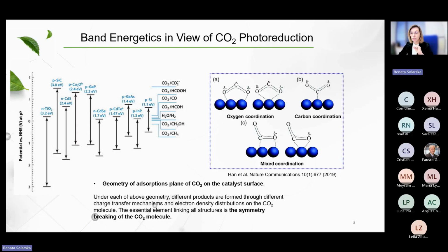So once we are at the surface, it's clear that we are working with the substrate, but the driving force for this process, which occurs at the surface, is in the bulk, in the structure. So the absorption of the light and the production of the charge carriers within specific time scales are very sensitive steps in the CO2 reduction. All these elements must occur at the same time. So this is challenging. The challenge lies in the material structure and the material's surface, and progress might be made by taking all of these into account together.